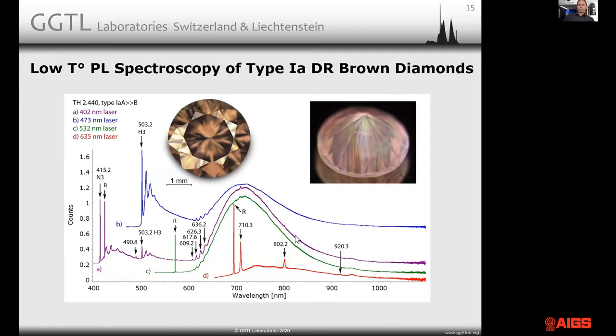So whenever you see funny pink fluorescence in a brown diamond, that's what causes it. Now, the intensity of this band obviously determines whether the final fluorescence that you see is pink or green, because, as you can see, you also have N3 centers, which cause blue fluorescence, and you have H3 centers, which cause green fluorescence. Now here, the very dominant defect under this excitation is the 710, hence you have this pink fluorescence.